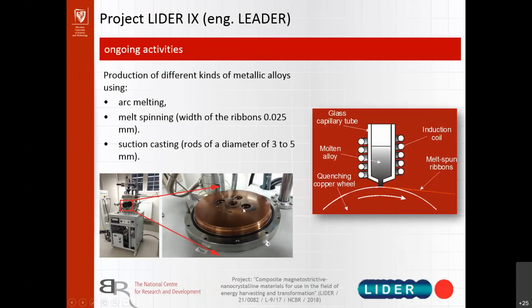And with arc melting, we are just melting the elements themselves together, and after that, here we have a chamber where we can also use suction casting, as you can see here. With this method, we are able to obtain rods with a diameter of 3 and 5 millimeters. But what does this method give us? The method gives us a very high cooling speed of the material.